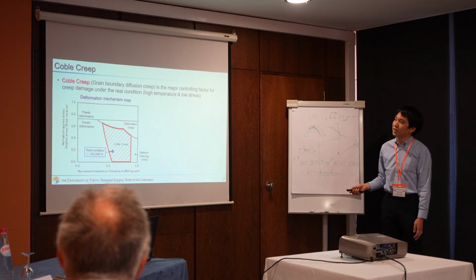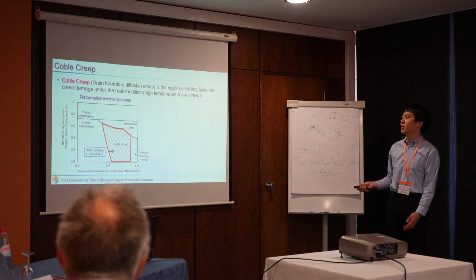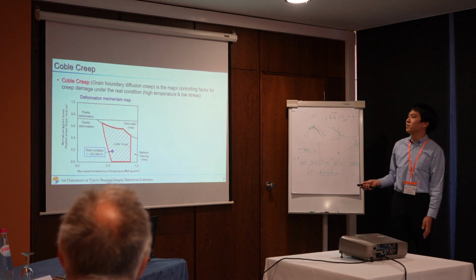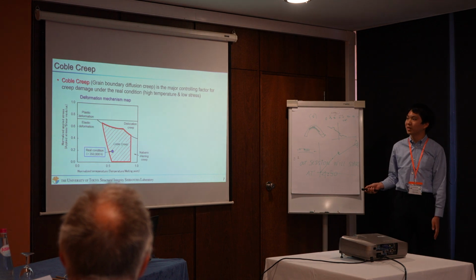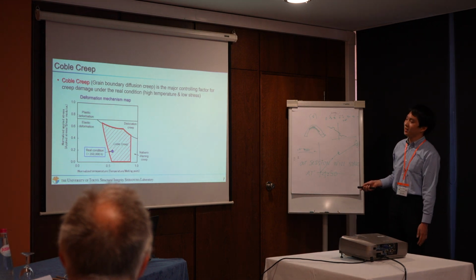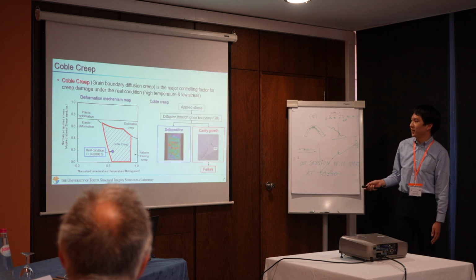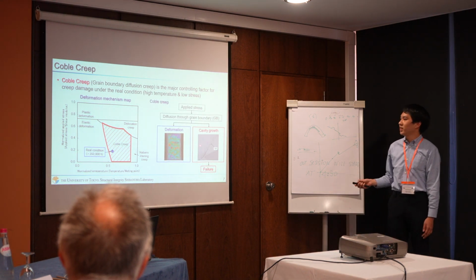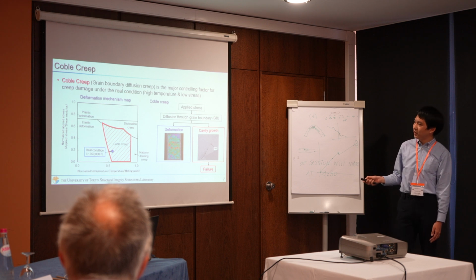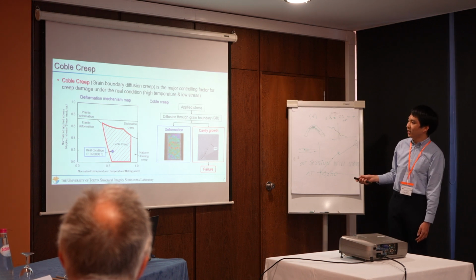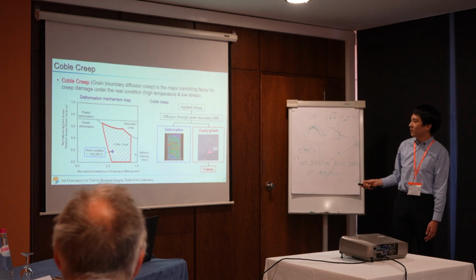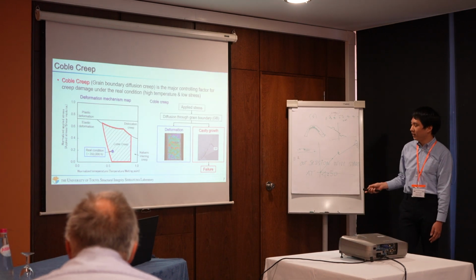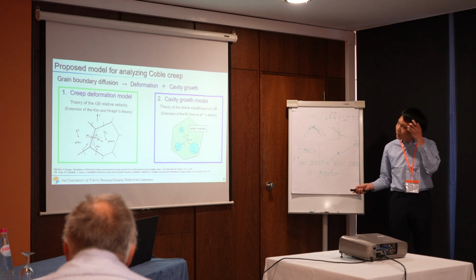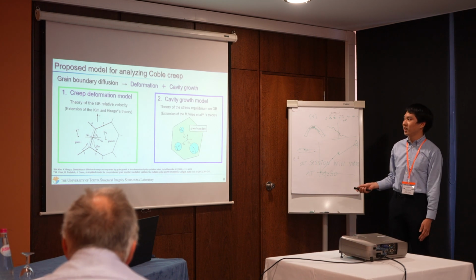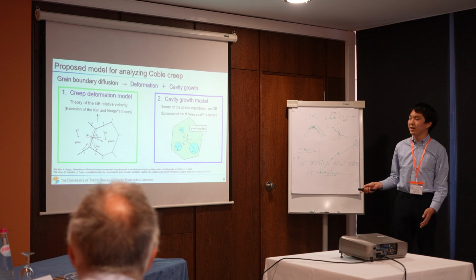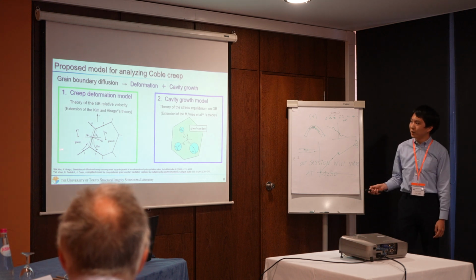First, under the real condition, higher temperature and low stress, Coble creep is a major controlling factor for creep damage. I'll explain Coble creep briefly. First, stress is applied, then diffusion occurs through the grain boundary, and deformation and cavity growth occur, and finally failure occurs. So the grain boundary causes the deformation and cavity growth, so we made two models, a creep deformation model